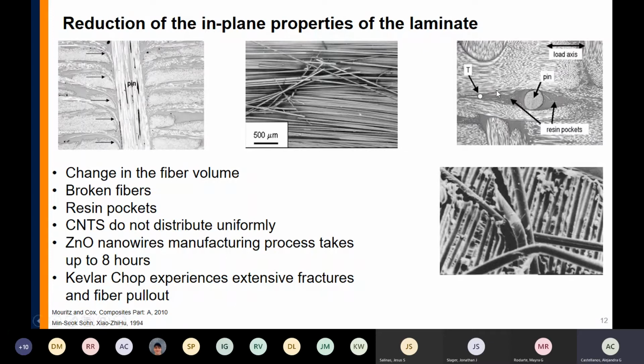And then another problem, on your top right hand over here, as you can see on this picture, is that on the pins, when you put them in, you will see some resin pockets around the pin. So that's a big problem because that's where the delamination or damage will start. Remember that cracks will always try to look for the path of least resistance, and the least resistant on the composite will be these resin pockets.